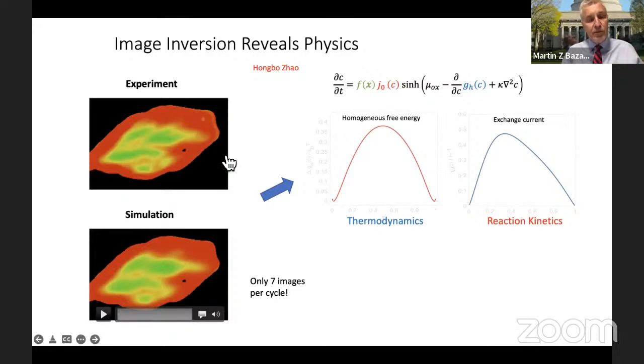And we apply this learning procedure to the model that I showed you before with this sort of Cahn-Hilliard reaction type model that I described. It's technically a Butler-Volmer dependence, this hyperbolic sine in this case. But the important thing is that we fit 3 different functions, as I'll now explain.